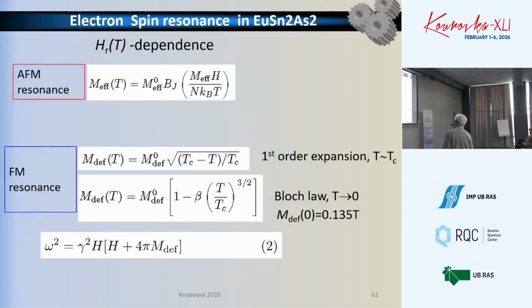Now, to describe the temperature dependence for the antiferromagnetic resonance, we use a standard textbook formula where BJ is the Brillouin function of magnetic field over temperature. For the ferromagnetic resonance, we also take textbook formulas. There are two inputs. One follows from first order expansion in the vicinity of a critical temperature like this. And another is the Bloch law, which is applicable as T approaches zero. Everywhere we apply the magnetization in a zero field, as I said,